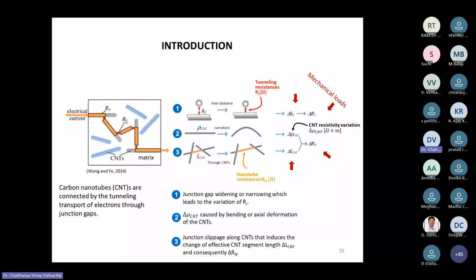So with that gap, tunneling is happening between the two nanoparticles, and then the electric current is passed through these nanoparticles and flows through this. So due to this electric current, there is a change in resistance of the material. Based on the change in resistance, we can know how the material is going to fail in future, or what the life of the material is. We can use this material as a sensor. Like this we can use CNTs, and carbon black, which are spherical particles. We can see how we can design and develop these, and how we can make these electrical paths conductive.